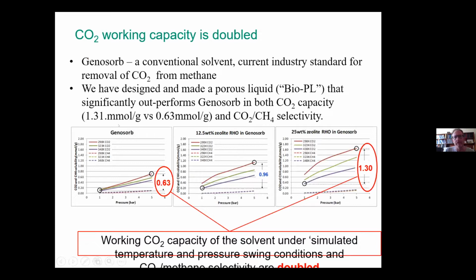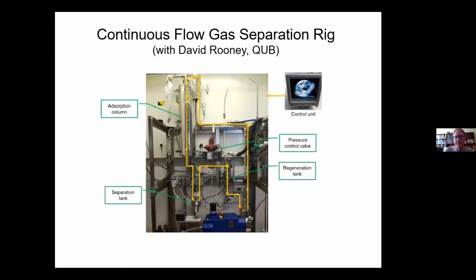And for Genosorb, the solvent itself, we came up with 0.63 millimoles of CO2 per gram. And you can see that's roughly doubled in our porous liquid on the right here. So basically it works. Also notice that the dotted lines here, these are the methane uptake, and that stays really low. So we've increased the capacity and the selectivity for CO2.